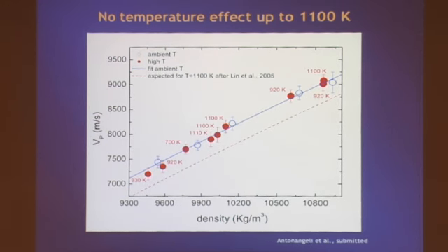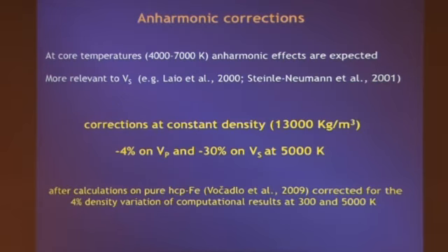However, the temperature of the core is not 1100. So for that, depending on the model, the temperature is supposed to be between 4,000 and 7,000 Kelvin, where all ab initio calculations suggest an anharmonic effect. Different calculations might give different amounts, but they all tend to agree that this can be particularly relevant on the shear velocity, especially for temperature approaching the melting.